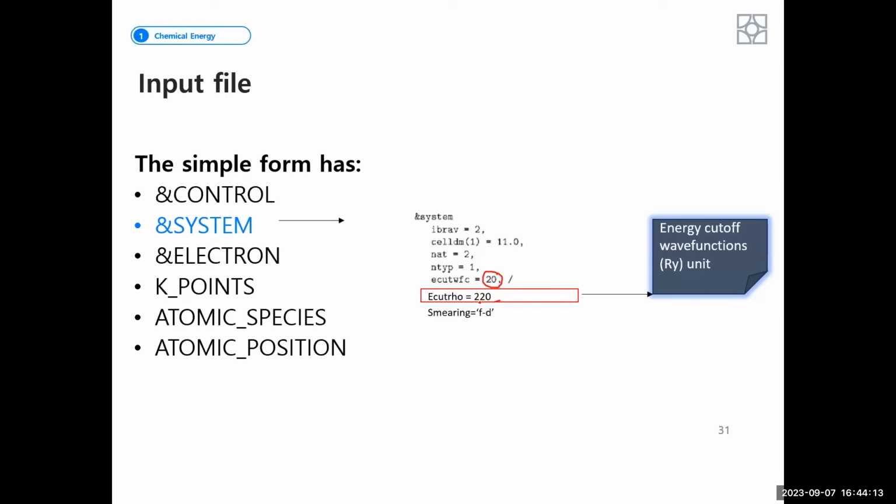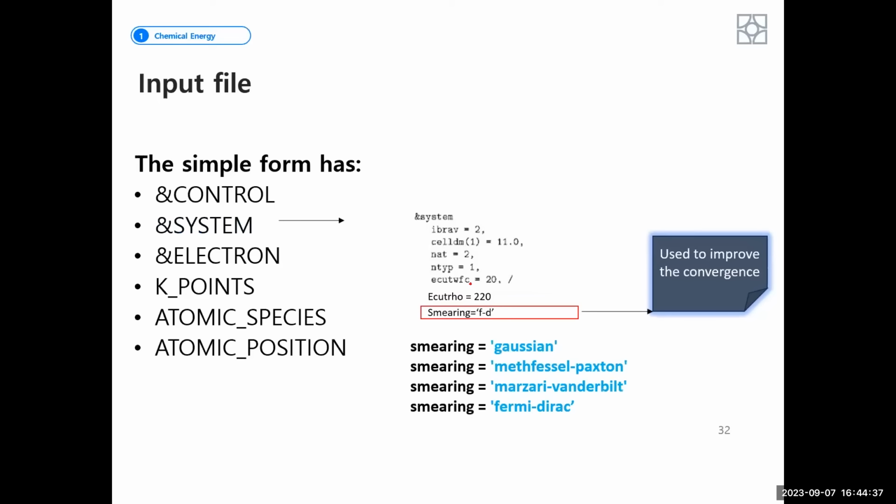This value can be 6 times or 10 times, depending on the material we are dealing with. For example, in metals it could even be 12 times, I mean the best result, while the average range has to be from 6 to 10. However, these two parameters are related, and they are also correlated with the K points.